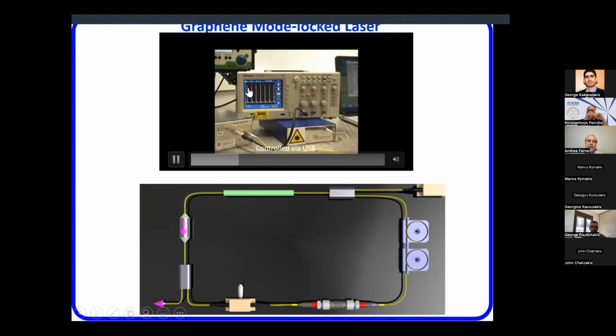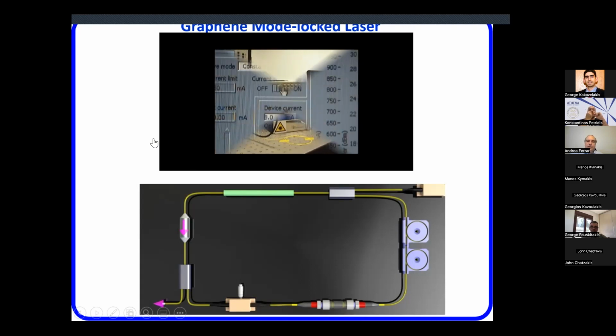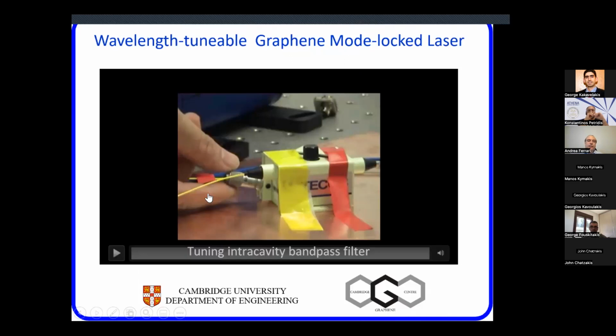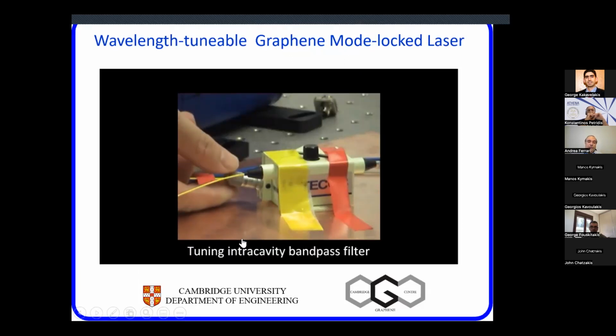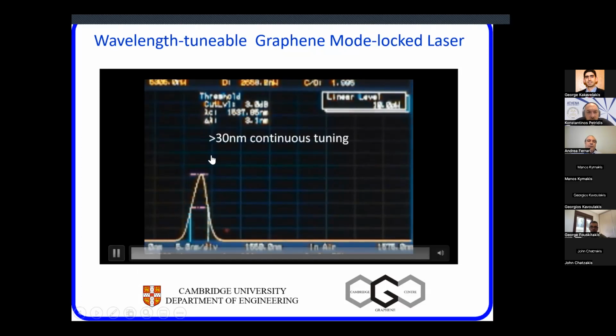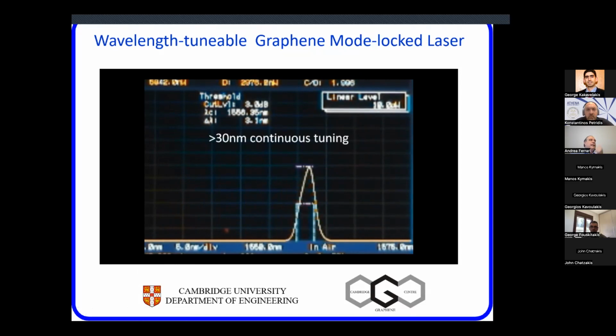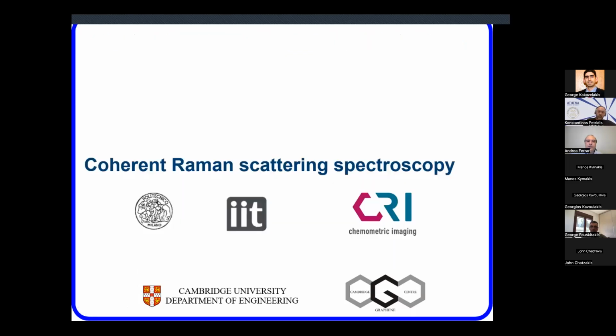And this was connected. You can see the laser pulses here after connecting to a photodetector. But what is more interesting is this second movie, because by tuning this bandpass filter, I am able to get a continuous tuning of the emission, thanks to the Dirac cone. It works at every wavelength. And in fact, the limitation is not the graphene, it is the optical fiber, the erbium doping. It's the gain of the erbium, it goes off after 30 nanometers. The piece of graphene will work at every wavelength. So this brought us to the next step, which is the development of coherent Raman spectroscopy.